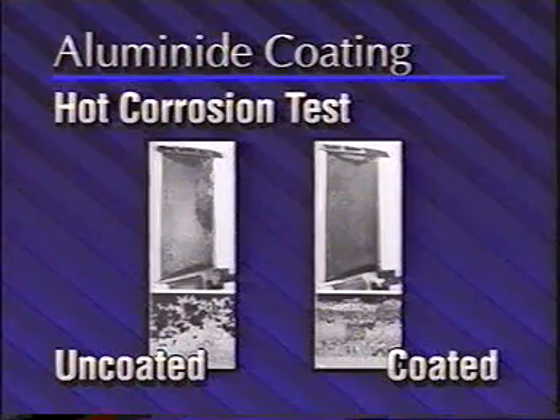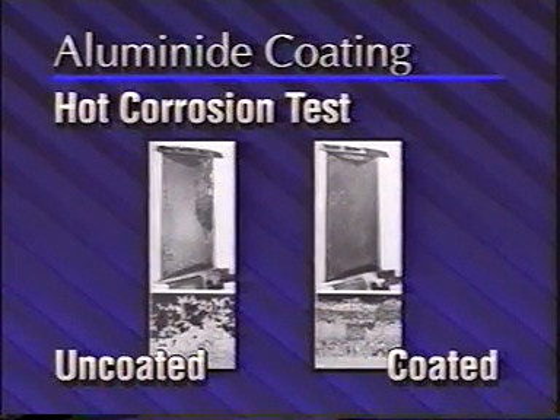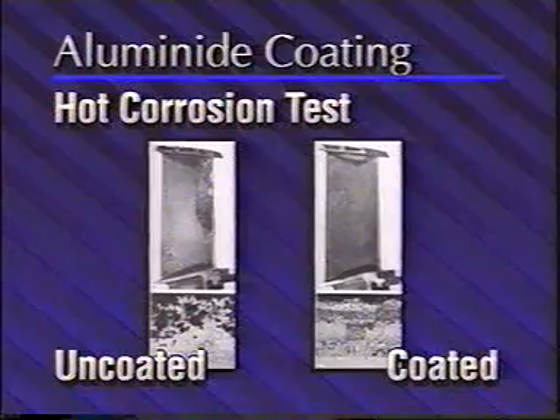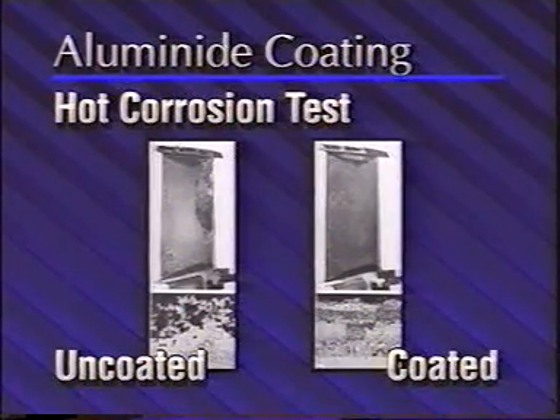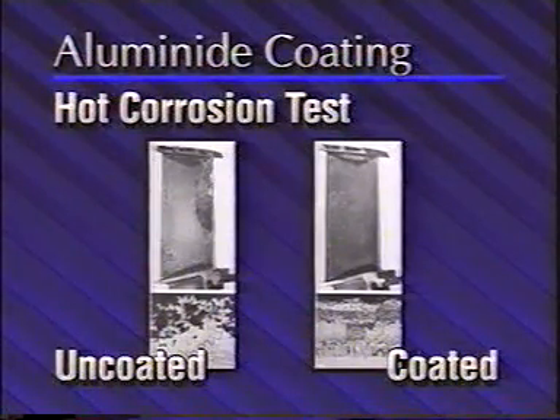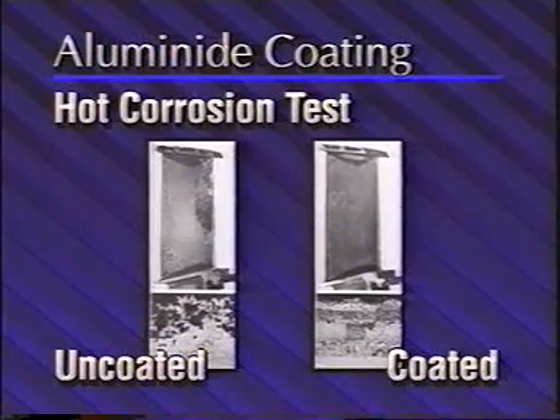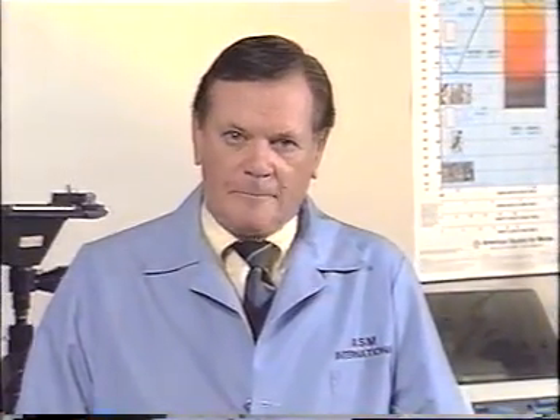An uncoated turbine blade after 118 programmed cycles shows severe degradation by hot corrosion. The same nickel-base alloy with a nickel aluminum protective coating after accelerated hot corrosion testing in an engine is only slightly degraded. The aluminum-rich coatings, such as the aluminide coatings, successfully extend the life expectancies of gas turbine engine blades and vanes. Another class of high-temperature corrosion-resistant coatings is applied to surfaces as complex cobalt-base alloys. The coatings are applied by electron beam vapor deposition or low-pressure plasma spraying.